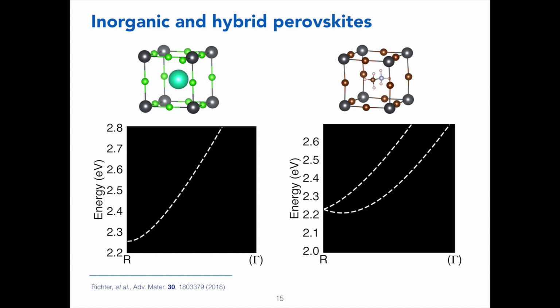Another thing that we can learn from the dynamics, which again has to do with dynamic disorder, is taking us back to the perovskites. So this is a piece of work that we did in collaboration with the experimental people here, led by Felix Deschler. And what we're doing here is comparing two perovskites. On the left, we have an inorganic perovskite, cesium lead bromide, where the cation is a cesium atom. And on the right, we have one of these hybrid perovskites, methylammonium lead iodide, or lead bromide. I can't quite remember whether it's bromide or iodide.